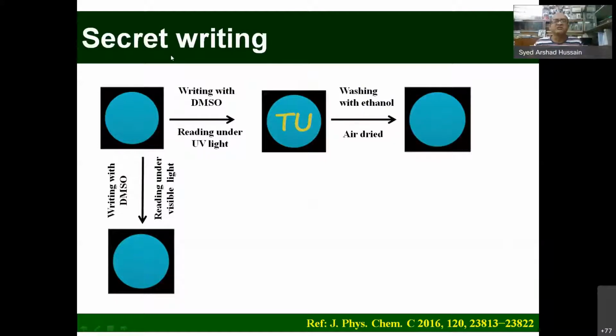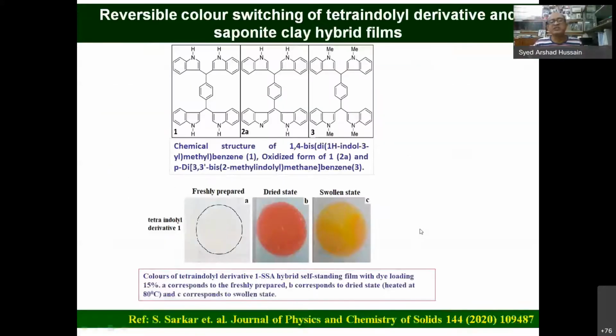How? So this is our as-prepared film. With DMSO we write, say, TU on the film, and then we observe with the naked eye under ordinary visible light, no color change, nothing is observed. But when we expose it under UV light, you see that TU is written. That means it can be used for secret writing. Again, washing and drying, the original color comes back. So it's a very good supramolecular system.